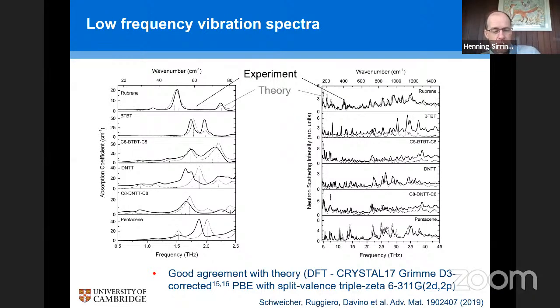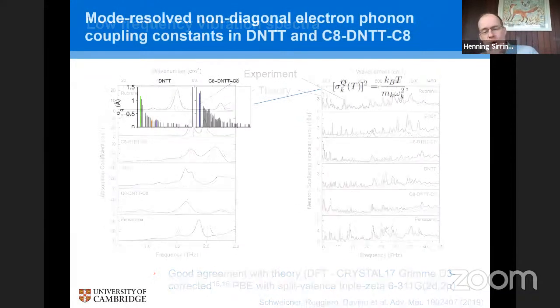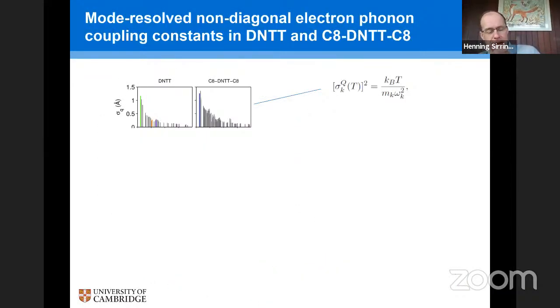We can describe these modes very well with density functional theory, high-level DFT, and then we can essentially do a mode-by-mode analysis of the electron-phonon coupling. So you typically start with these individual modes, this comparison here of two different molecules: DNTT, I showed a picture of that in the previous slide, and then an alkyl-substituted DNTT where you have essentially two alkyl side chains substituted to the end of the molecule. And you can see here these different modes. The x-axis here is a frequency axis, and the y-axis is the amplitude.